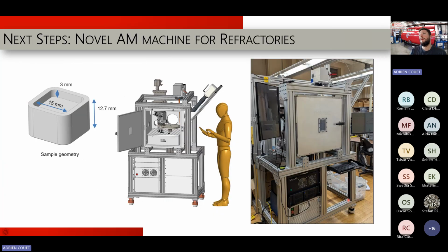Another thing we're doing is we're trying to develop additively manufactured materials for refractory alloys. So we are developing a completely new machine for additive manufacturing that is able to print tungsten, molybdenum, tantalum alloys in small cubes like that. And so this is a piece. This is the additive manufacturing machine that has been built. And it's done by a colleague of mine in mechanical engineering, with whom we work. And so this is a very exciting new approach to obtain refractory high entropy alloys, for instance, for our research.